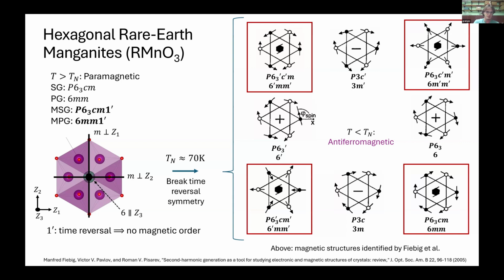But below the Néel temperature, you break this time reversal symmetry operator, and you can have subgroups of 6mm1'. So you may still have time reversal symmetry tied to one of the individual symmetry operations, and this gives you the different magnetic structures that you can have. You may have transitions between these structures, spin rearrangements, once you're below the Néel temperature. So for example, I believe for yttrium manganite, you start in 6'mm' at 70 Kelvin, and then somewhere around 4 Kelvin or at high magnetic field, you transition to the 6'm'm point group through this antiphase spin rotation. This is the kind of thing we are looking to see in these manganites.